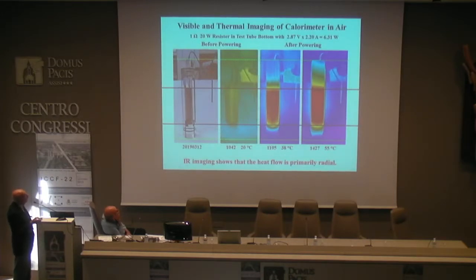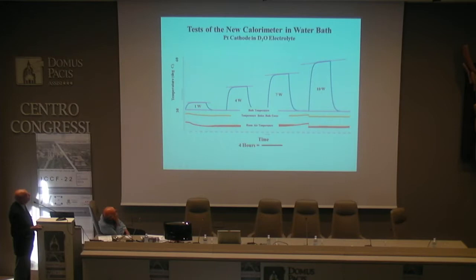We wanted to know about the thermal behavior, so we put the calorimeter out on a table, put a resistor in to heat it, visible in the photograph on the left here, and then these are, as you see, infrared pictures. And the bottom line here is the imaging shows that the heat flow is primarily radial. There's not a tremendous amount of heat that escapes out the ends, which is good, of course, from a data analysis viewpoint.